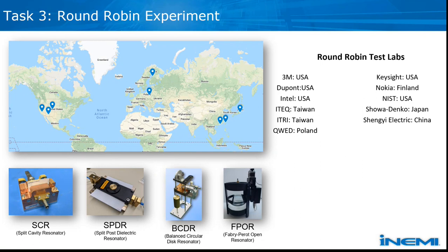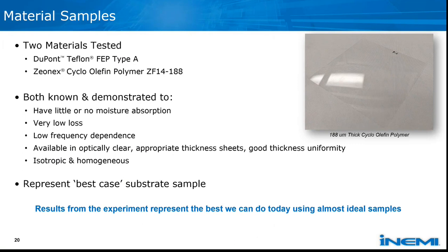Out of the task 1 and 2, we also had identified a number of material samples. And if you go on to the next slide, the material samples that sort of fell out as natural candidates for this round robin experiment were the Teflon series materials and the COP polymer materials. These are materials that have been used in industry for a while as internal references generally, and they've been known through experimentation and the literature to basically have very little or no moisture absorption effects. We know that moisture absorption in realistic samples is a problem in terms of reproducibility, so we wanted to do this test with a very stable set of materials so we could really understand what the variability was looking across different labs, so that we could demonstrate the best case scenario in terms of extraction of material parameters to understand how well industry as a whole can do this.